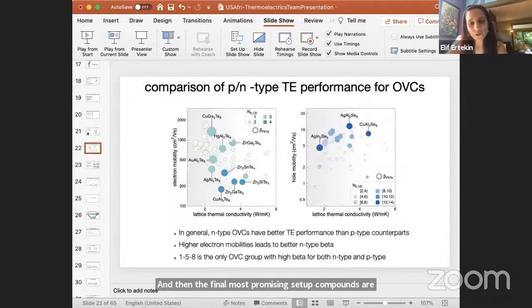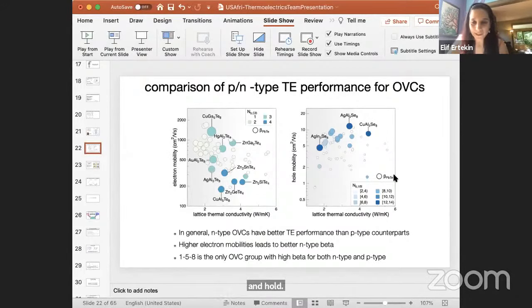Okay, so this slide shows some of the results of our assessment of the quality factor beta for our 54 OVCs. The diagram on the left shows beta for N-type doped, and on the right for P-type doped semiconductors. The x-axis shows the predicted lattice thermal conductivity, and the y-axis the predicted carrier mobility, electrons and holes. So again, good thermoelectrics here would appear on the upper left. One observation, which you can see just from comparing the scale of the y-axis for electrons and holes, is that N-type ordered vacancy compounds are predicted to have better thermoelectric performance than their P-type counterparts, largely due to these larger predicted electron carrier mobilities compared to holes.